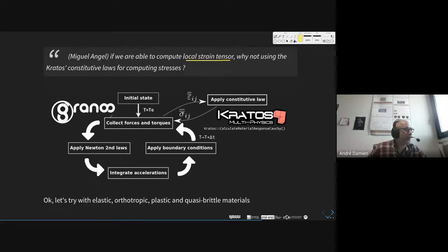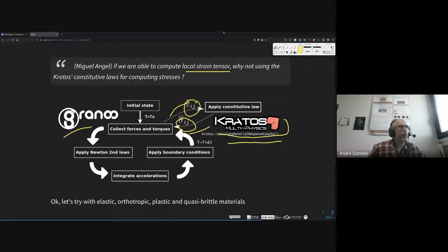So here you have the main discrete element algorithm, and here you have the dialogue between the Kratos package and the Granoo software. So we simply send the strain tensor to Kratos multiphysics, and we apply these routines, the calculate material response Cauchy, and it gives a stress tensor, and we treat the stress tensor inside the Granoo part to produce the right reaction force. And now I propose to show you some tests with this architecture.